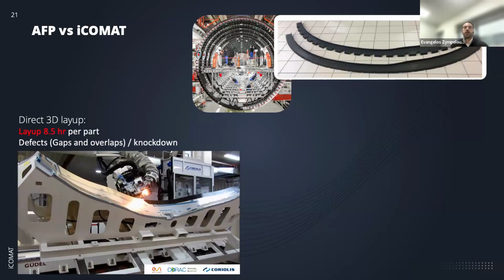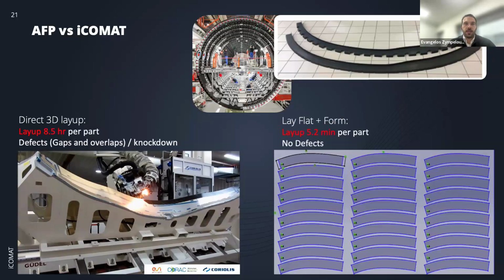So if we use our lay flat and form approach while using very wide tapes, so we're talking 8 inches wide, then we can do the layup for one frame in about 5.2 minutes. So this is really going from 8.5 hours to 5.2 minutes. Here you have defects, here you have no defects. So we're not talking about a 2% improvement here. This is an order of magnitude improvement in terms of production rate and also cost.